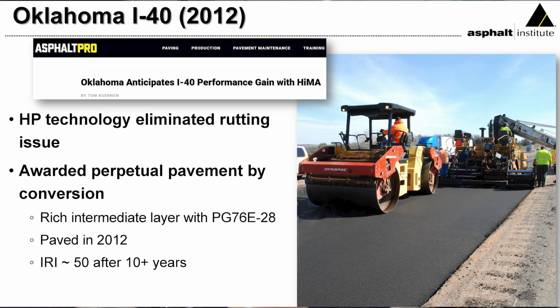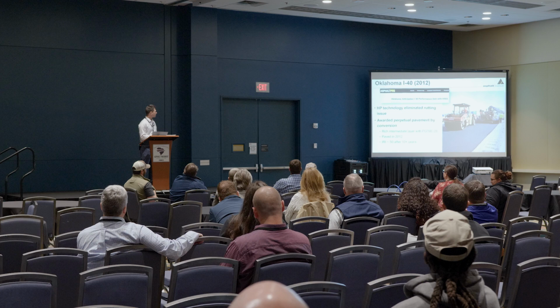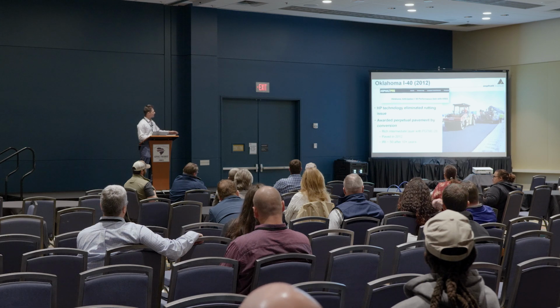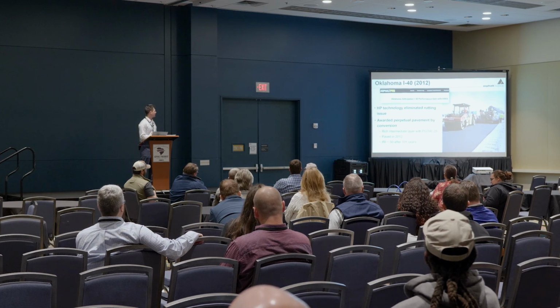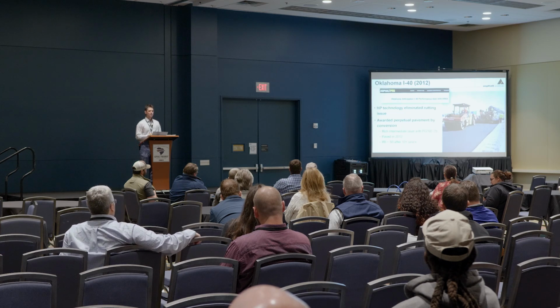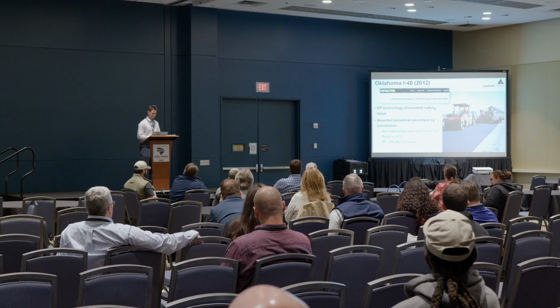Another example, and this one was featured in the Asphalt Pro, was Oklahoma's I-40. And they're primarily using HP as a rich intermediate layer for rutting resistance. And this project, again, was very successful and actually was awarded a Perpetual Pavement by Conversion Award by the Asphalt Pavement Alliance. And after 10 years, is maintaining an IRI of 50.